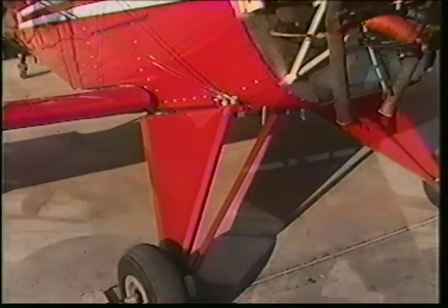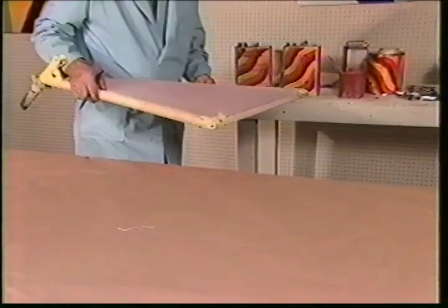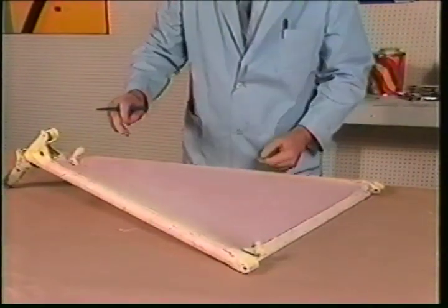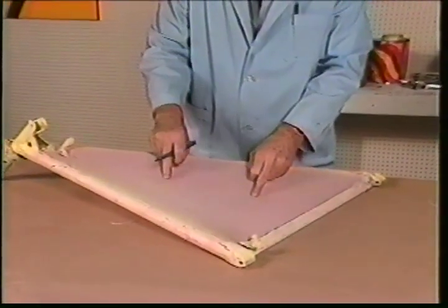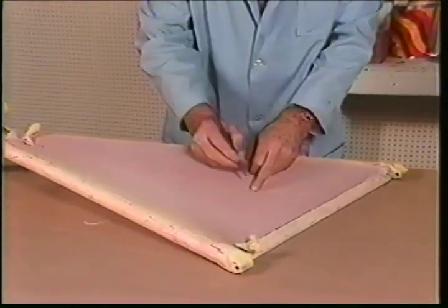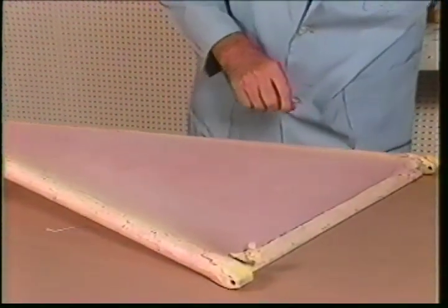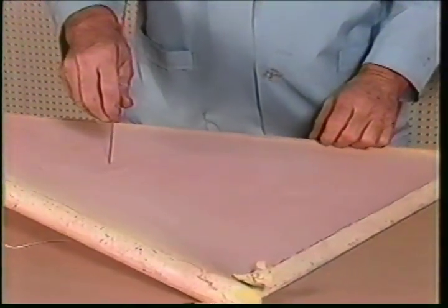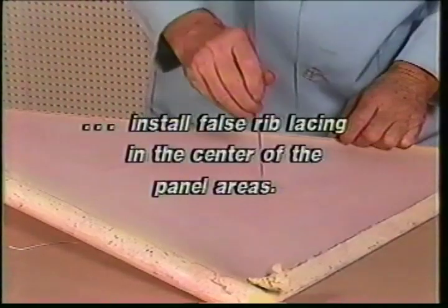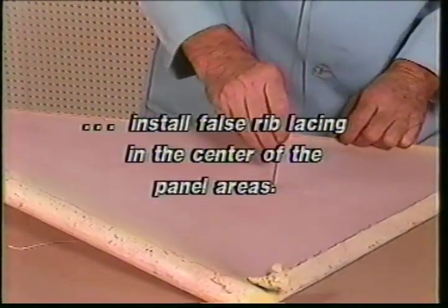Sonic shock waves from large engine exhaust blasting directly on fabric-covered landing gear legs also causes coating fatigue cracks regardless of the type of fabric and coating. These design deficiencies don't appear until 200 or 300 hours flying time, and the fabric covering materials are always blamed for the problem. A practical method to change the natural frequency of fabric panels, such as landing gear legs and horizontal stabilizer, and reduce the drumming, is to install false rib lacing in the center of the panel areas.